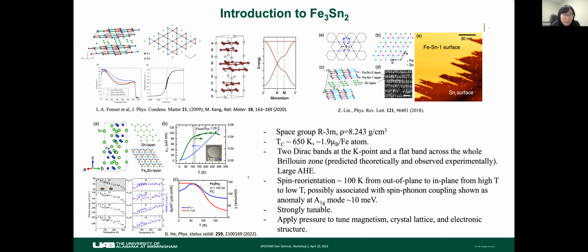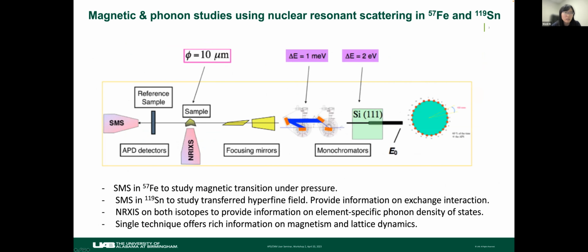Also, some calculations show that the system is extremely tunable. The spin orbit coupling and the band structure are extremely tunable, and also have a large dependence on the magnetic configuration. So motivated by this series of work, we applied pressure. Hopefully we want to control the magnetism, crystal lattice, and also look into the electronic and band structures. That's why we chose the nuclear resonance scattering technique, because in this system it is so convenient. It's iron tin, and both elements have Mossbauer active isotopes. So it's really an ideal technique to study this system in terms of the magnetic transitions and lattice dynamics.